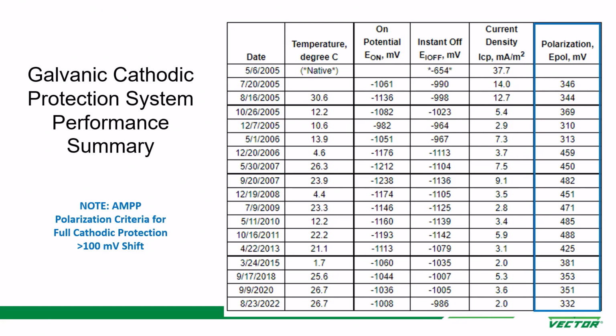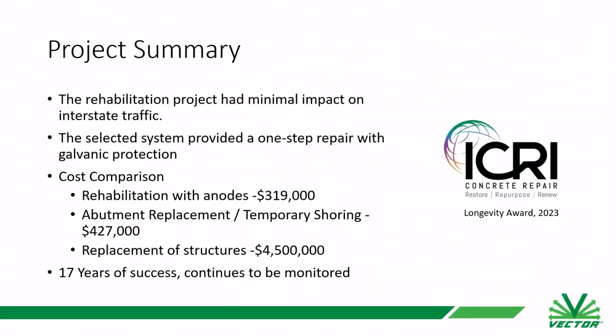The cathodic protection requirement to say a structure is fully cathodically protected is that it has to have a depolarization of greater than 100 millivolt shift. And you see all these numbers are significantly over 100 millivolts. So these anodes are significantly providing a high level of protection to the embedded reinforcing steel. So it's a really good example of long-term durability with a lot of monitoring.